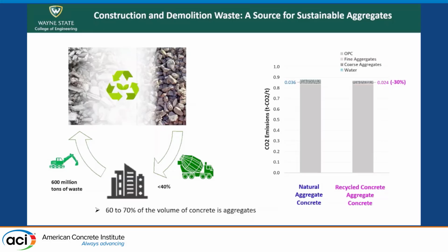As I show here, by completely substituting natural aggregates with recycled concrete aggregates, we see only a 30% decrease in CO2 emissions, but we have to take into account that concrete consists of 60 to 70% aggregates by volume. So the effect of that is multiplying.